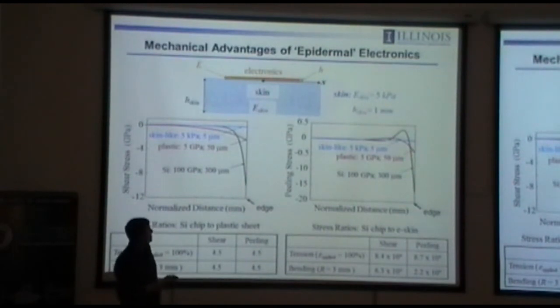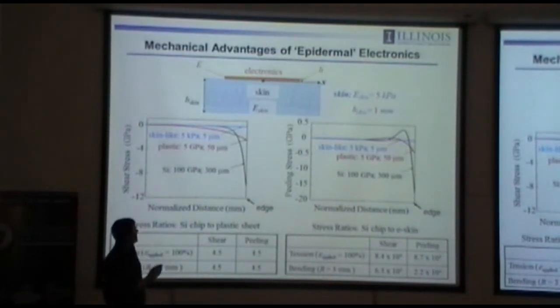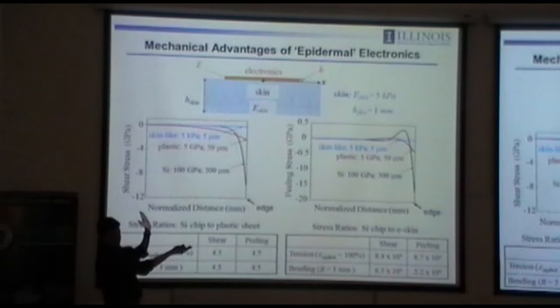construct. So you can do analytical calculations of the interface stresses that could drive delamination between a piece of electronics and the skin in a generalized sense, in which the electronics is just considered as a slab of material with modulus E and thickness H. It's sitting on a piece of skin that has a modulus here, E skin, and thickness, let's say, 1 millimeter, 5 kilopascals on the skin. It's a little bit low, but just for the purpose of discussion, that was the assumption. And then you can compute not only the shear stresses that develop at the interface, but also the peeling stresses, both of which can initiate delamination and cause the device to flake off of the skin when the skin is deformed.